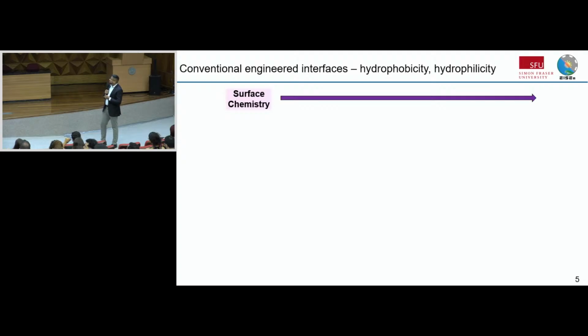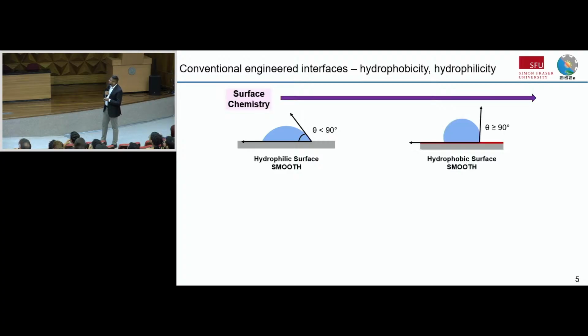So the first thing is hydrophobic materials and hydrophilic. So again, looking at surface chemistry as one lever, you can have two types of surfaces, a hydrophilic surface or a hydrophobic surface, and that's defined by the contact angle. So if the contact angle is less than 90, it's hydrophilic. If it's greater than 90, and a good example is a non-stick pan. In a non-stick pan, a coating like the red coating makes a hydrophilic material like steel hydrophobic, right?